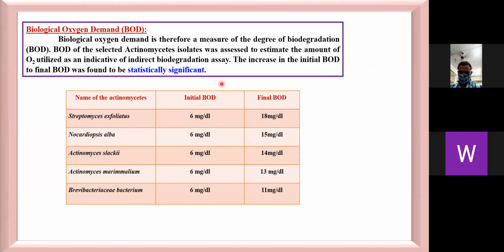BOD of the selected actinomycete isolates was assessed to estimate the amount of oxygen utilized, which is an indicator of indirect biodegradation assay. All five actinomycete strains show an initial BOD of 6 mg per deciliter, whereas at the final BOD after 1 month, Streptomyces exfoliatus and Nocardiopsis alba presented the maximum BOD with 18 mg per deciliter and 15 mg per deciliter, followed by Actinomyces slackii with 14 mg per deciliter. For the other actinomycetes, mammalium and Brevibacteriaceae, 13 and 11 mg per deciliter respectively.